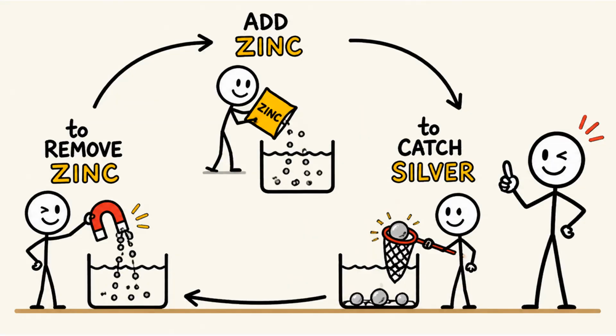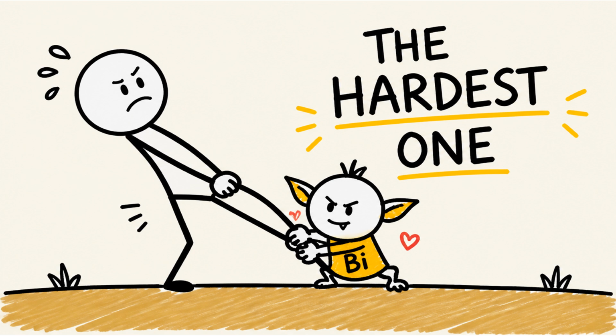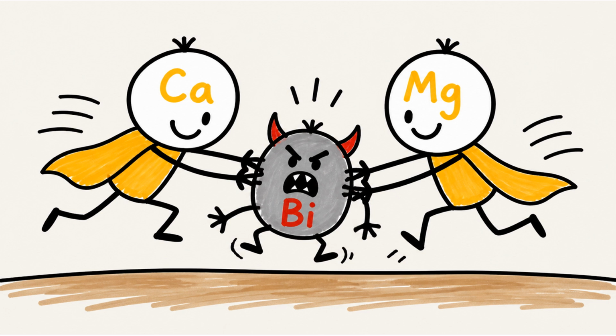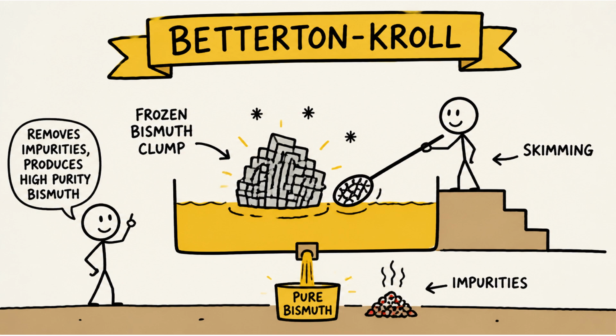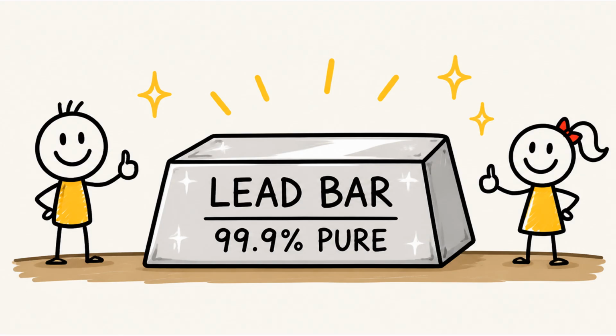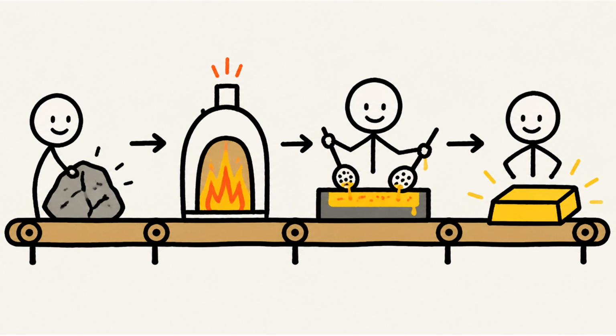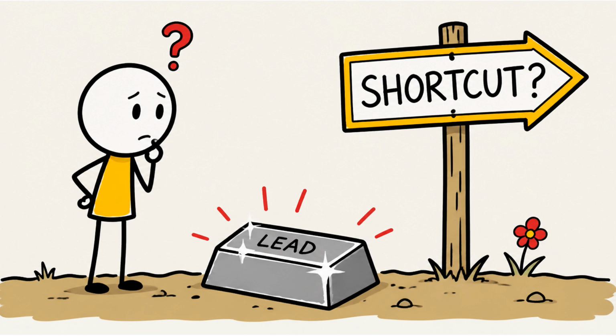Almost done. There's one last stubborn impurity, bismuth, and it's the hardest to remove, so it gets its own dedicated process. They stir in calcium and magnesium, which grab the bismuth and freeze it into a solid clump that floats to the top and gets skimmed away. That one's called the Betterton-Kroll process. A final cleanup, and at last you have it. Refined lead, 99.9% pure or better. From a gray rock, through fire and skimming and a half dozen chemical tricks, to a gleaming bar of pure metal.